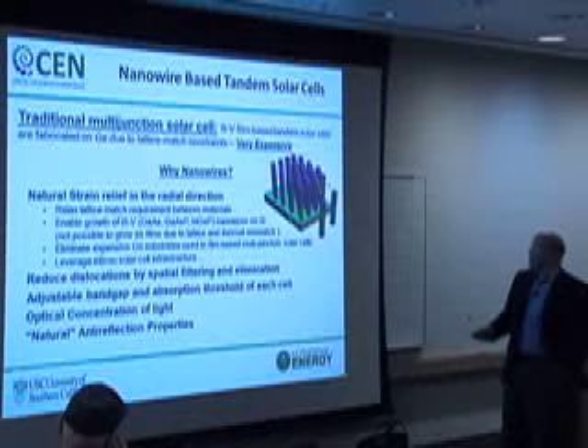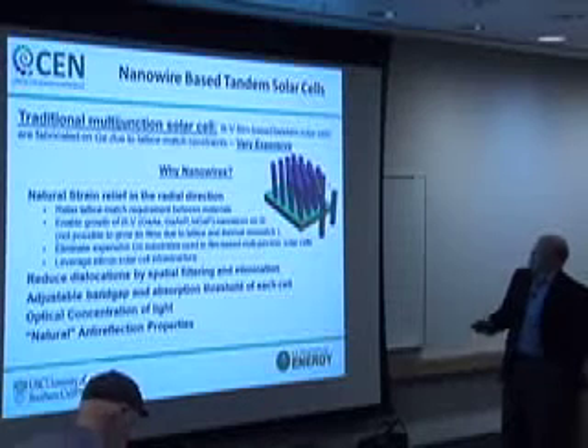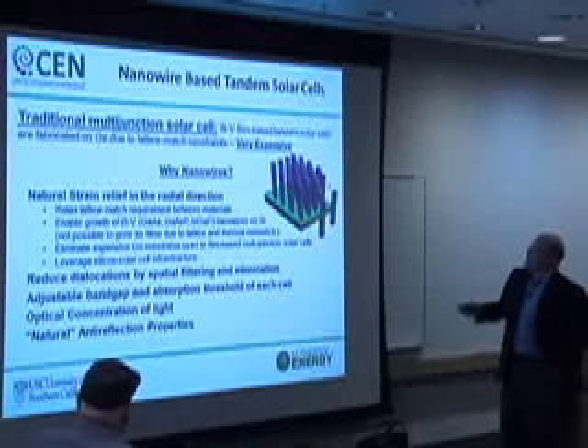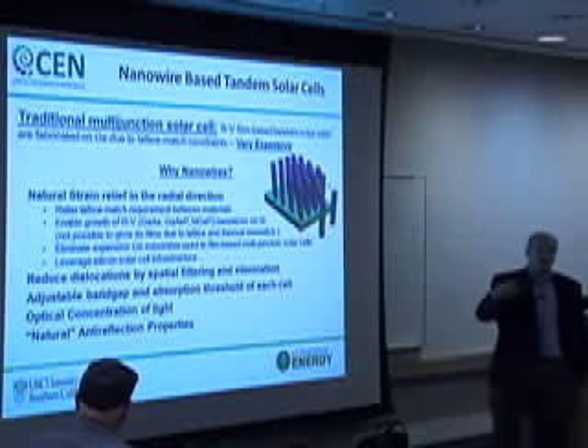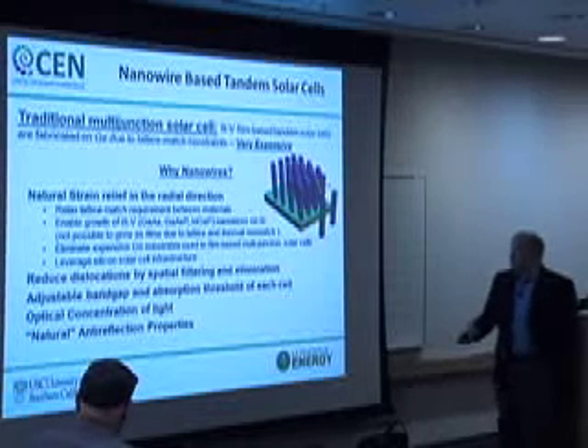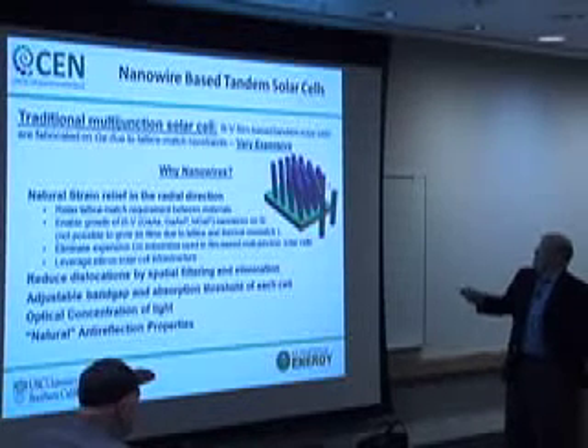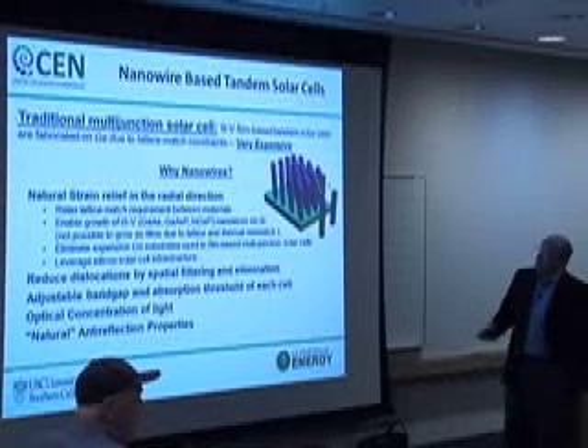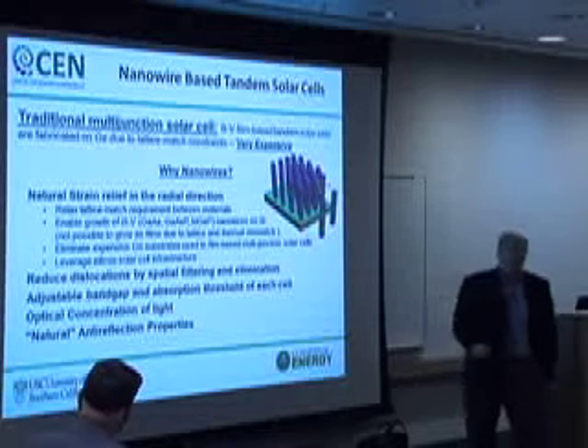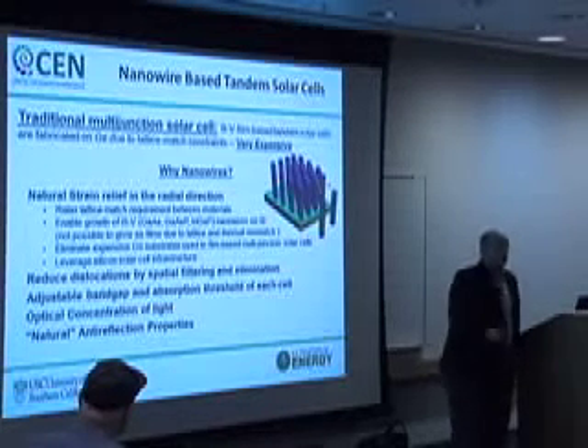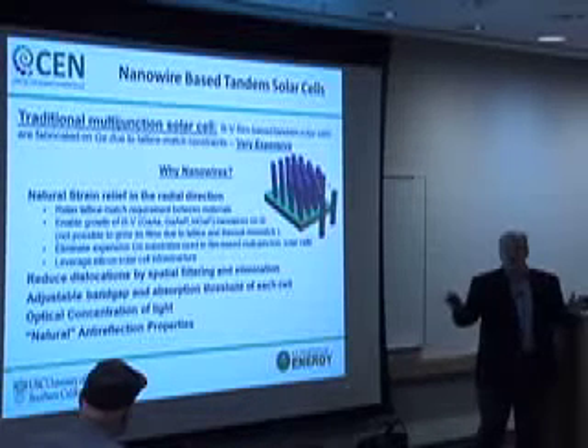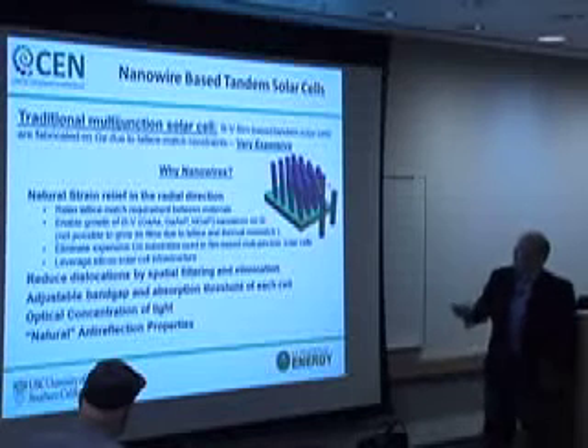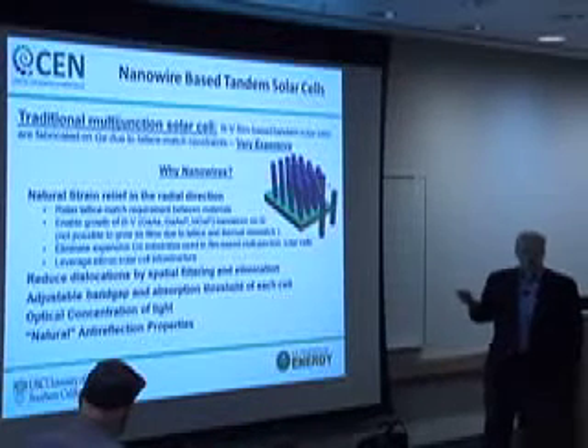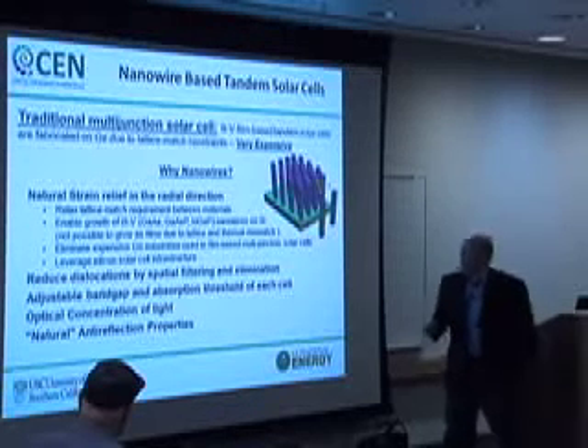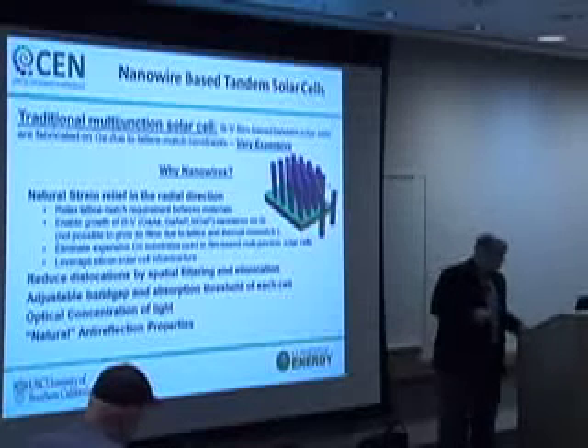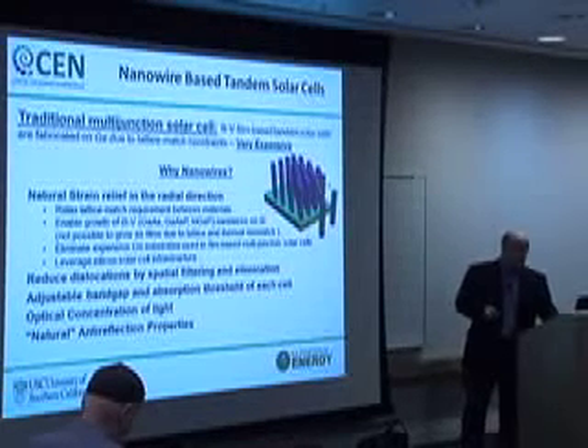We can vary the composition here and adjust the band gap and absorption threshold. And what I'll show you in a minute is that this kind of a design actually gives you a measure of optical concentration. And I'll explain that in just a minute. In addition, because of light scattering amongst these rods, this kind of a structure actually has natural anti-reflection properties. One of the big problems in a multi-junction solar cell is getting low reflectivity over the wide energy band that you require for a multi-junction cell. And these kinds of structures automatically give you that kind of low reflectivity. So there are a number of reasons why it's interesting to look at this. And that's what we've chosen to do.